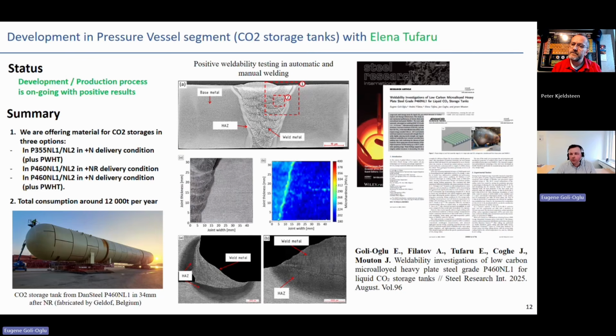For the new products, we are performing weldability testing to be sure that after welding, our steel heavy plates will still be in good shape, and will guarantee the level of mechanical properties which will follow the requirements of the standards. And there are two options: either to do it here at Dansteel or close by, or we could also send the plates or coupons to our customers, and then they will weld them using their equipment and test them and give a green light, or if there is some issue, we'll have some discussion on how to improve it.